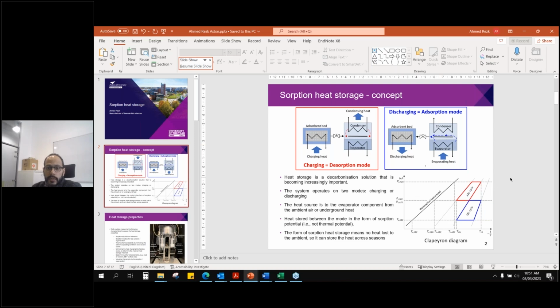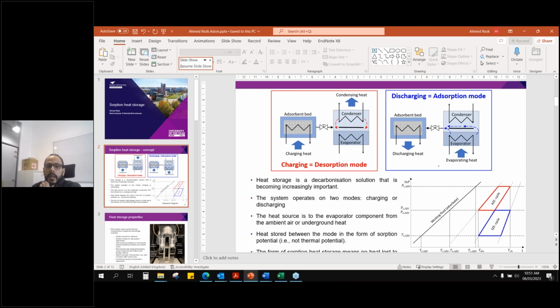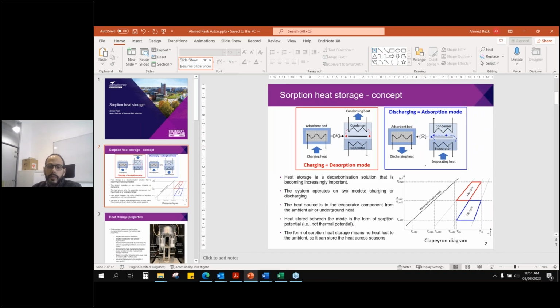You might be aware of what sorption heat storage is. It is a device where you can store heat in the form of sorption potential, not heat potential or temperature difference potential. Assume that we have a reactor containing a sorbent material like silica gel, zeolite, or activated carbon. When you have surplus heat, you can use it to dry this sorbent material, and the sorbate, which might be water, ethanol, methanol, or other gases, is stored in another storage. When you expose the sorbent material back to the sorbate, the adsorption heat can be retrieved again. So this way we can charge and discharge.